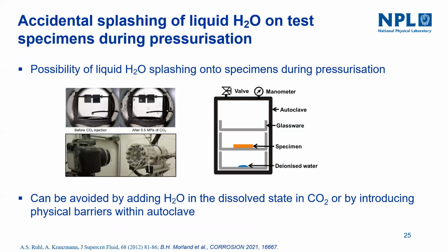The possibility of water splashing on the test specimens was revealed by in situ visualization during the testing. Morland et al. custom built an autoclave having a visual window. This is the initial droplet. While pressurizing the autoclave, you can see a splashing of water over the whole autoclave. You can see the water splashing on the test specimens. So corrosion initiates at the start of the test itself from the splash water rather than from the condensed water. In this case, the corrosion can be higher.